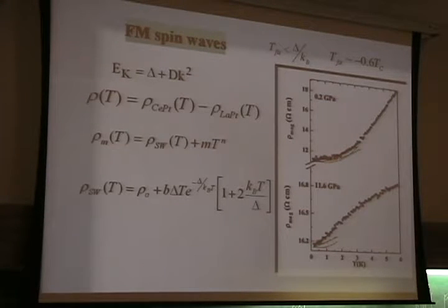You see how it is. The spin wave contribution is dominating the behavior, and also for high pressure we still can get a very good fitting of this behavior. This is just to point out that this is in the case of an isotropic ferromagnet, okay? Because there is another scenario for antiferromagnetic spin waves that has a slightly different formula for the resistivity, and in general, when you try to fit with the other kind of formula, you cannot describe this behavior here. Okay, so it's a hint for us that the spin wave scenario for an isotropic ferromagnet is working from low pressure up to high values of the pressure. It means that the system is keeping its ferromagnetic character even at high pressures.